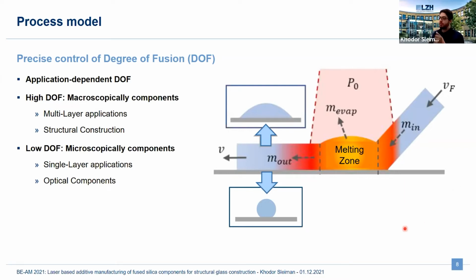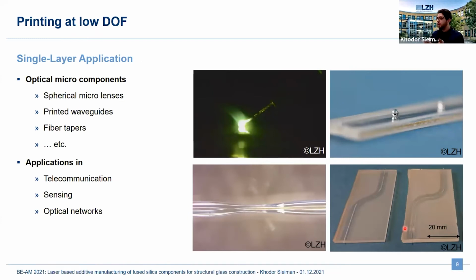A low degree of fusion is also very interesting, because there the form of the glass filament is still visible in the cross-section, and it's better for microscopic components. For example, single layer applications like optical components, which I can show you here. Yeah, so we could print spherical micro lenses like this, where the glass filament is just heated up and then deposited at once onto the substrate. This can be used to guide light in optical networks, and also the printing of waveguides, where the light can be guided through this deposited fiber, and fiber tapers, and all kinds of other optical components. This can be used for telecommunication, sensing, optical networks, or, yeah, you call it.